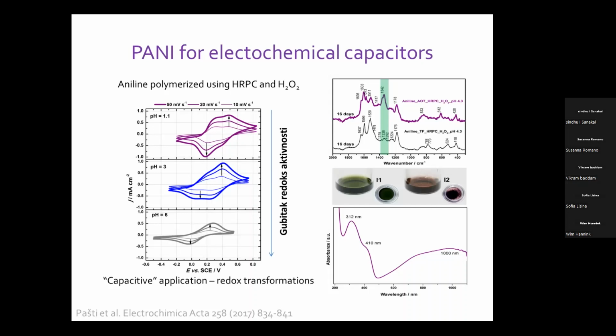So in principle, if you look at these cyclic voltammetry curves, it's not rectangular as one could expect for supercapacitive applications. But there is a very narrow window where these redox processes are taking place. So in principle, you can get a material which has a capacitance of 700 farads per gram, which is really high and an appreciable value, which you can use, for example, for some hybrid devices. So that would alleviate problems of typical double layer capacitors, and you get more energy stored in the system.